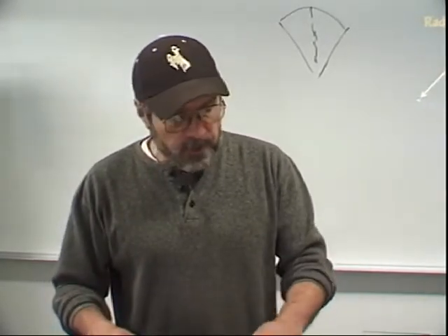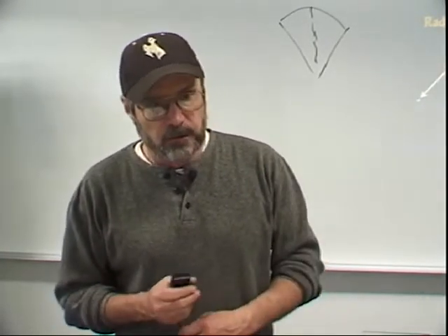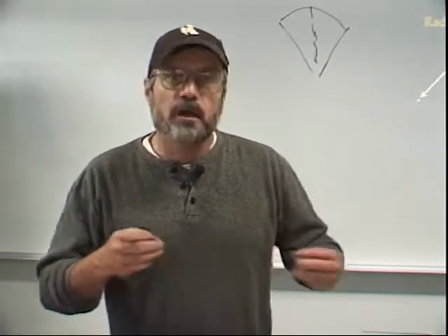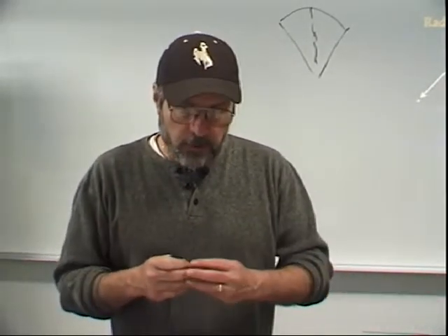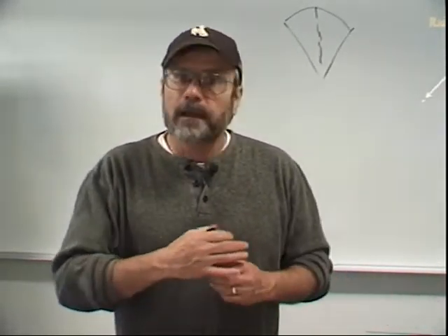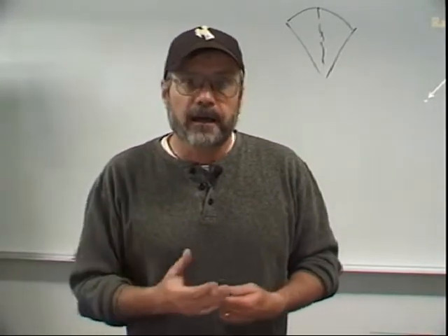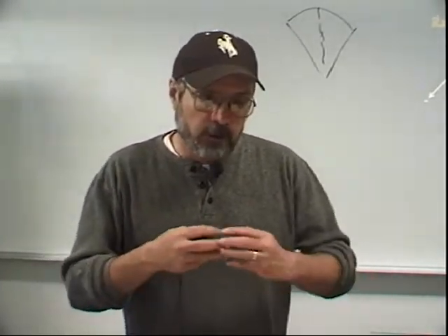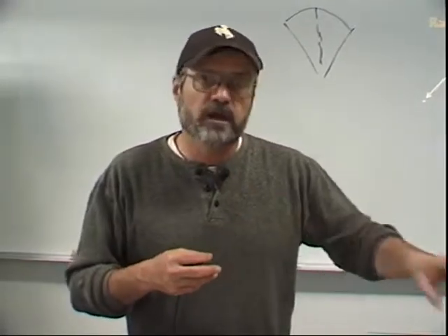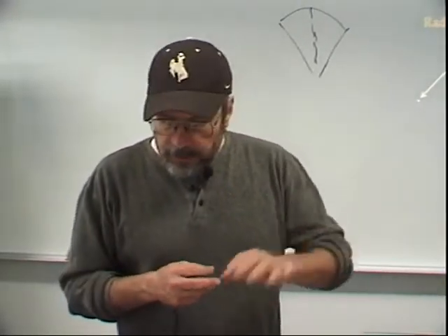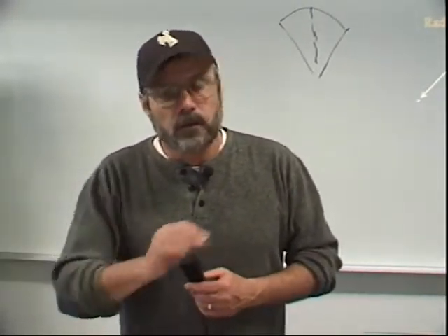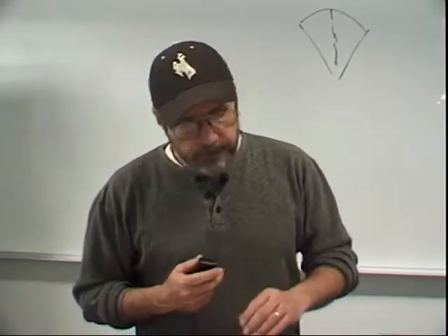And the other type of tungsten inclusion besides the one we saw on the film is the shed that I talked about earlier, where you're using too high an amperage, and the outer layer becomes loose, and it'll just shed and be shot into the weld, and that'll kind of look like pepper. It'll be peppered all through there, all through the weld.